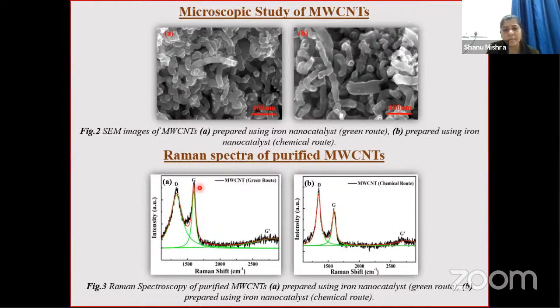As you can see from the graph also, the G intensity in the green tea synthesized iron nanoparticle sample is higher than this one. And here we see a less intense but broad peak at around 2700 inverse centimeters, which corresponds to the G' band, and it generally shows the long range order of crystallinity in CNT.